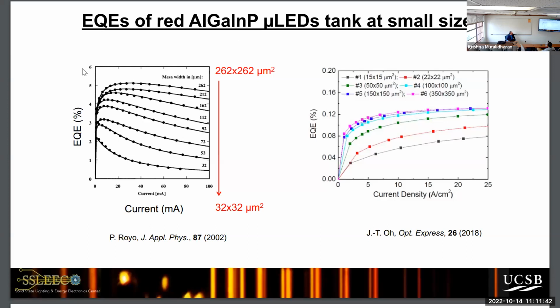Sorry. So this is external quantum efficiency. So the big problem we faced is that when you make these materials smaller, the efficiency dropped very quickly. So we didn't know why, and this was a problem we had not solved. So I said we had 90% efficient LEDs, but look what happens when you make them in the red. You're down to 6%, or even less. So this is a problem we had about 15 years ago. And even as recently as 4 years ago, we were only around 12%.